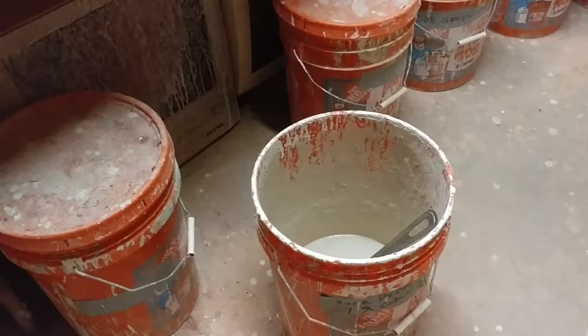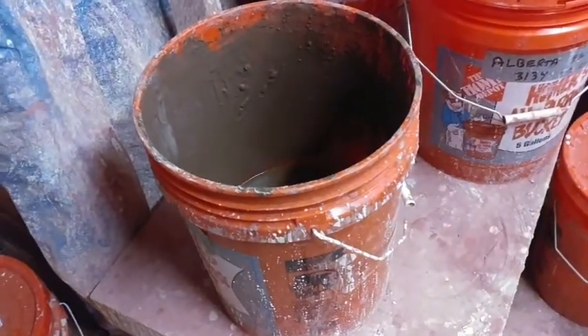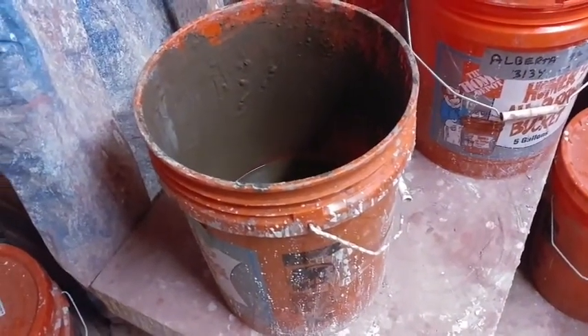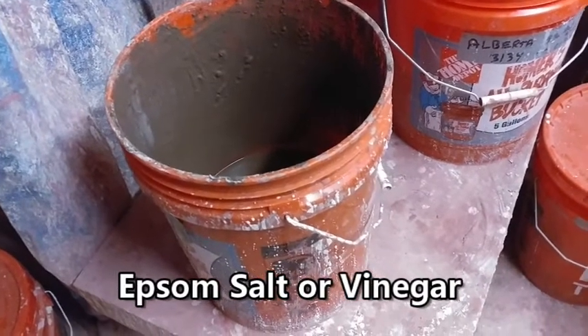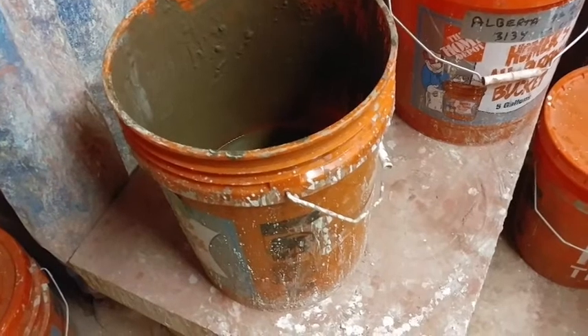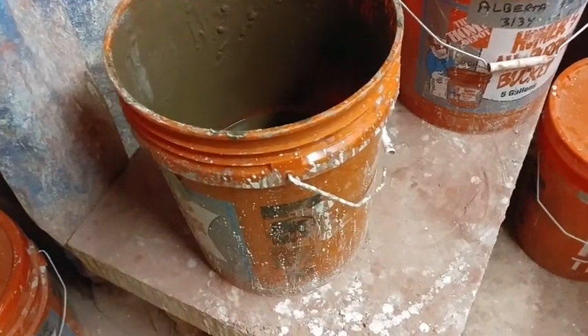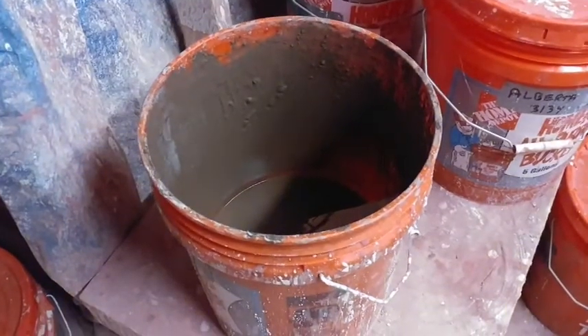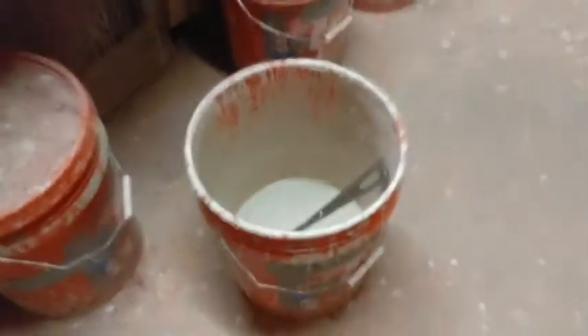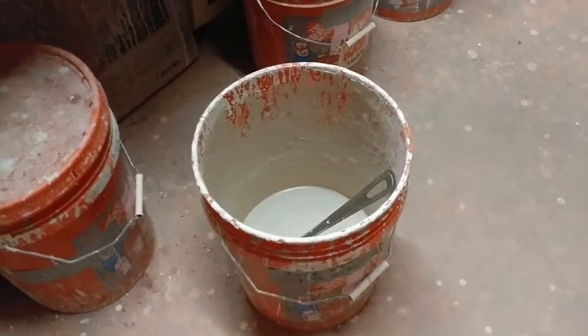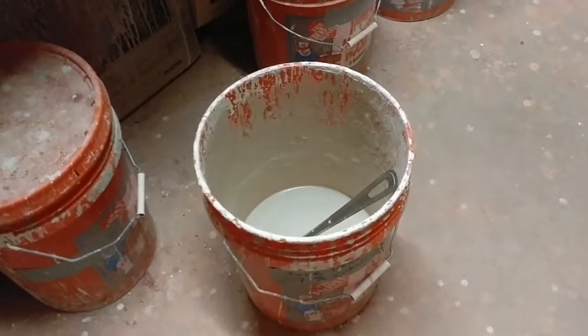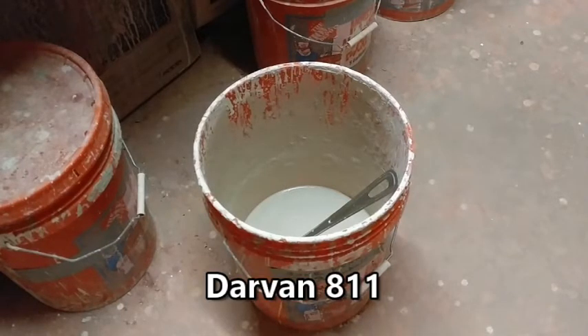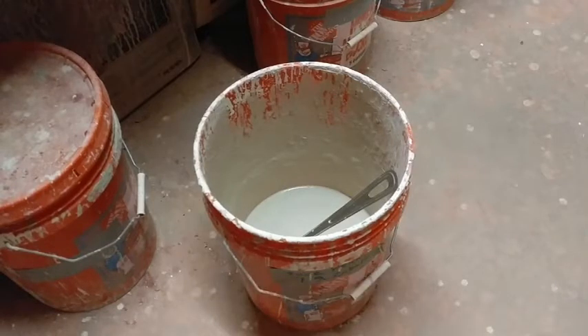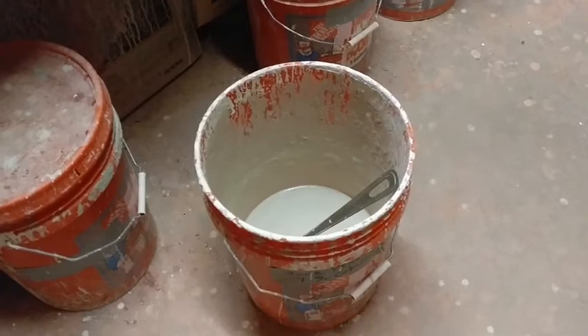And if you want to alter it, like let's say this glaze is more alkaline, and I want it to be more acidic, I can add Epsom salt or vinegar, and that will make it more acidic, making it more flocculant, giving it higher amounts of thixotropy. This glaze right here is very thixotropic. It's very acidic. If I wanted it to be more alkaline, I would have to add something called Darvan 811. So you can add Darvan 811 as a way to deflocculate it to make it less thixotropic.